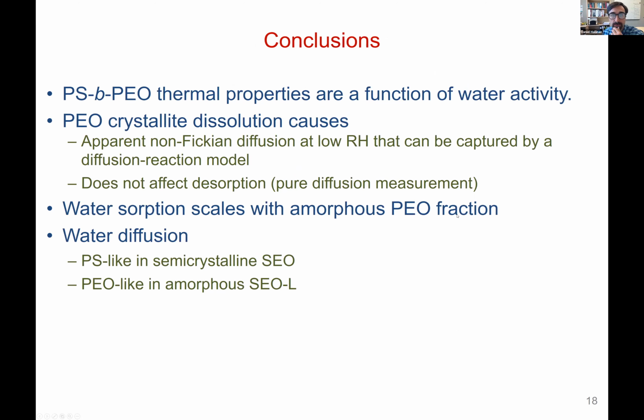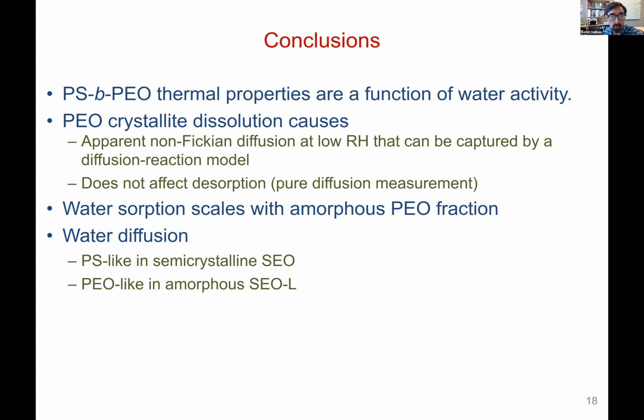So to conclude, we found that these amphiphilic block copolymers have thermal properties that are a function of water activity, and that was really our biggest contribution. I don't think that was realized before our work. We found that PEO crystals can be dissolved by water, and that the water absorption, the amount of water that goes into the polymer, scales with the amount of amorphous PEO, the amorphous hydrophilic component.